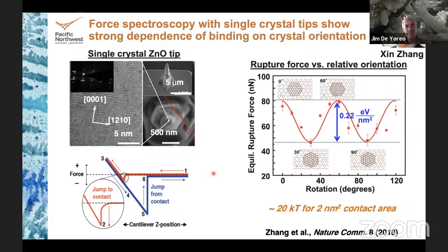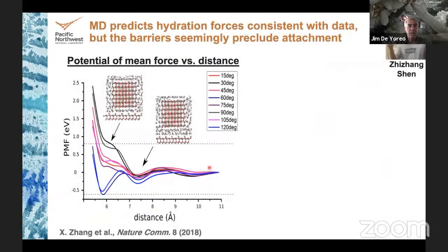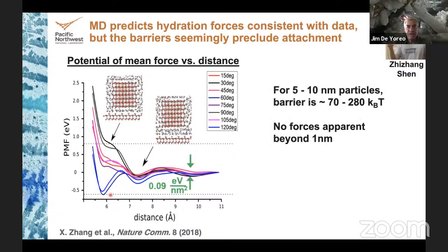If you look at the molecular dynamics simulations for the same system, it's pretty satisfying in the sense that you also find a potential of mean force with a deep minimum for alignment and a smaller minimum for misalignment. The difference here is very close to what you see experimentally, but we run into the same problems. In the zinc oxide system, we would predict that for 5 to 10 nanometer particles, the barrier is huge. Mind you, the surface area of these tips is more like 100 nanometers. And so it's impossible to push these surfaces together if these are the kinds of barriers that exist. In addition, there are no forces beyond a nanometer.